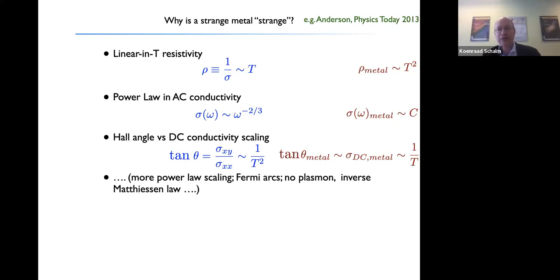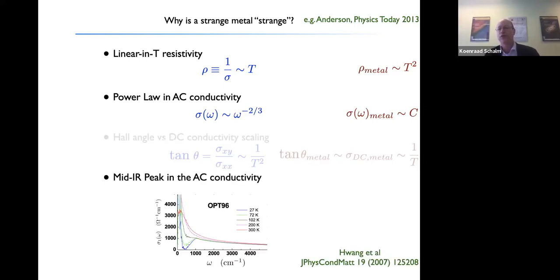There are many other aspects of a strange metal. These are 3 of the most famous ones. And there's a fourth one that I'm going to take into account in this talk. It's a lesser known one, but it's definitely there: in the AC conductivity, if you go to these higher temperatures, then you see not only this power law scaling, but you also see a mid-IR peak develop. Here you see that at the highest temperatures, 300 Kelvin, there's a small peak in the AC conductivity. In other words, the largest conductivity is no longer at zero frequency, but at some small frequency away from zero. This only happens at really high temperatures. At low temperatures, you have a beautiful Drude peak where the largest conductivity is at zero frequency. So these are aspects that a strange metal should explain.